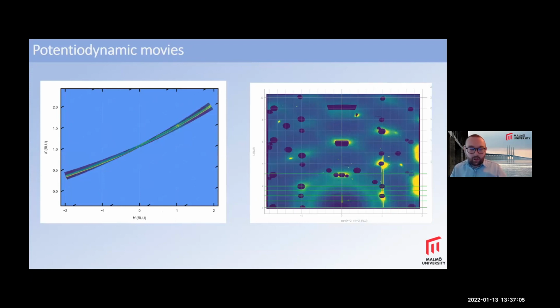We can also do sort of quick scans. So I think I'll play that again. So if we rotate the sample, and then we rotate it back around a small angle, we can see the sort of time evolution as we change the potential. So in this case, I just added an extra image at the end. So the next image that it's collecting, I just made a really bright image, so you can see how it's scanning. The reason that there's a thickness to that is because we're taking intensity in these masks, so up along the Z direction. And so that means that the pixels don't just fall in a neat line; they sort of spread out a little bit.